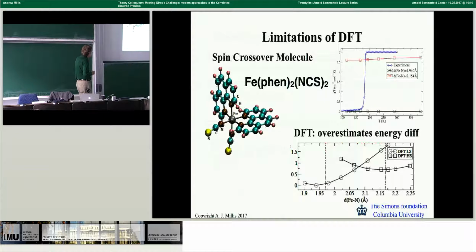Right? Now, this has been very successful, but it has a number of limitations. This is a simple and instructive example I want to show you based on work that Jia Chen did. This is a complicated molecule. It has an iron atom surrounded by stuff. All right? Now, it turns out that this iron atom can be in two states. A high temperature state where there's a magnetic moment. You see that here. This is temperature times the magnetic susceptibility. The fact that this is constant up here says that the iron has a free spin. Then at some temperature, boom, it goes to something which has no spin. So there's a high spin to low spin transition.